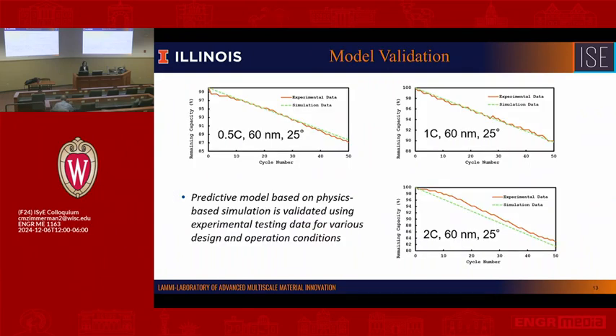And more importantly, we need to validate our model. Luckily, we got some experimental data from our collaborator at USC. They quantified the performance of the silicon anode with different thickness at different temperature, as well as different charging rate. Here I only present 3 examples, for the same thickness, the same temperature, but different charging rates. But we do have more results that have a better comparison between the experimental testing and our simulation results. This helps us understand how valid our model is.